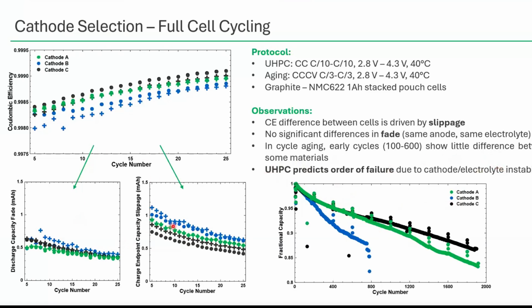So these UHPC measurements can predict this order of failure due to cathode electrolyte instability very quickly. It can tell us, once we separate it into these two components of Coulombic efficiency, where the failure is coming from. This becomes a lot more important later on when we're not just looking at cells where we're controlling everything and making very good apples to apples comparisons, but when we're looking at very different cells.